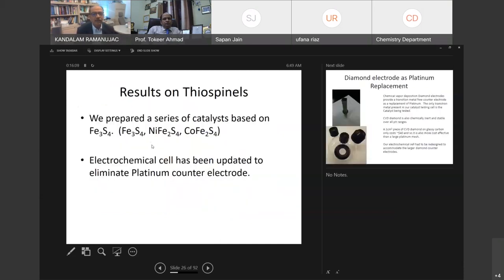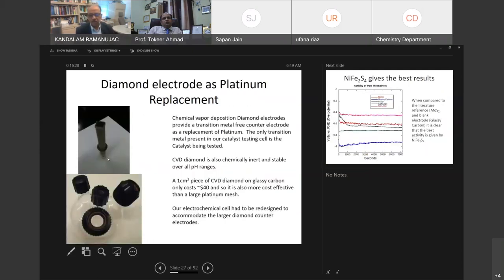So what we have done is, initially we started with three thiospinels: iron, nickel, and cobalt. In electrochemical cells, especially in three-electrode assemblies, generally people use platinum as a counter electrode, but we wanted to eliminate that too. So we used a diamond electrode, which is much cheaper, about $40, and that eliminates any possibility of the counter electrode acting as a catalyst in the electrolytic splitting of water. So you need to remove all possibilities. This is how we have done it.